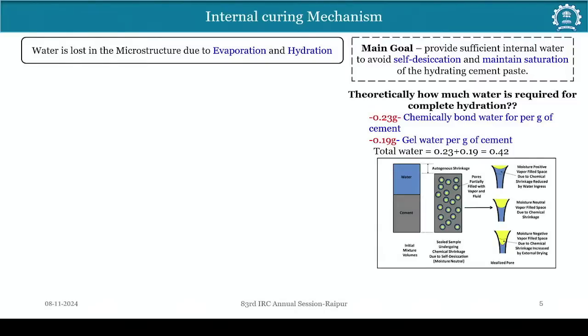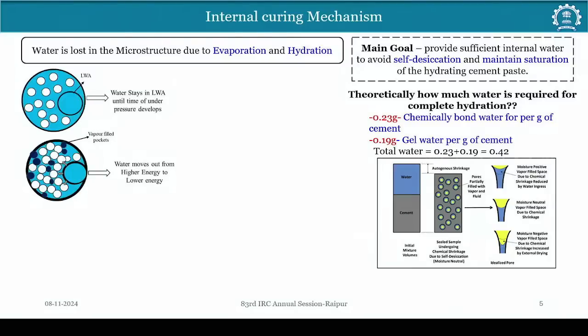In the graphs we can see that from the sealing, the capillary pressure is reduced. So, as seen in the figure here, the mechanism: the lightweight aggregate is usually basically like a sponge. It is like we are dipping it in water, it will hold a lot of water. It will release only when there is stress, like when we apply stress with our hand, it will release at that time. A similar thing happens inside the concrete too.